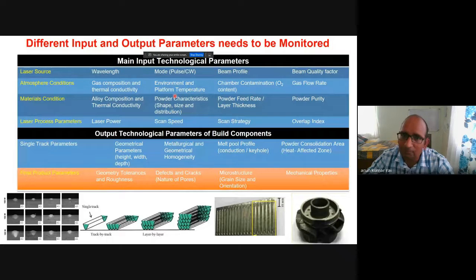And the fourth is the environment and platform. Suppose I have a substrate material whose thermal expansion is much higher than my deposited material. What will happen? Due to the temperature difference, cracks will develop in the deposited product. To avoid that, we do preheating of the substrate. When you do preheating, the delta T is reduced, and due to this, the generation of residual stresses from the difference in thermal expansion will be less, and that can lead to minimum crack formation or porosity formation.